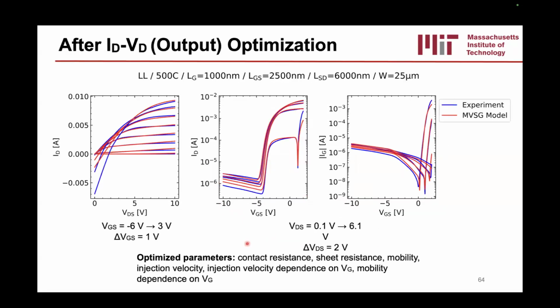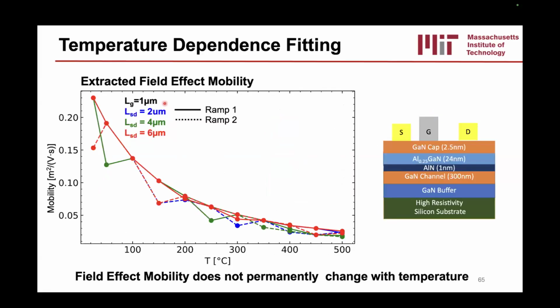We can optimize things like the contact resistance, the sheet resistance, the mobility, and the injection velocity. And now we can get a really good match in the output characteristics, transfer characteristics, and the gate leakage characteristics at very high temperatures in a semi-automated fashion. And the most important thing about this is that we can use it to really understand the device's physics. For instance, we can look at the field effect mobility, the mobility extracted from the transistor characteristics, for various device dimensions, in this case, 1 micron gate length and 2 to 6 micron source-drain distances.